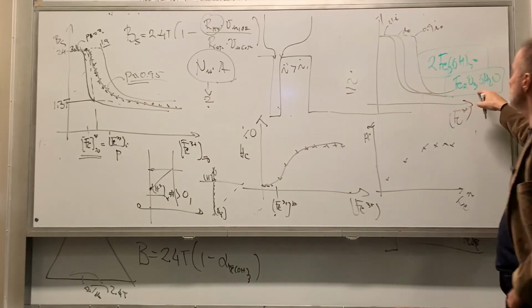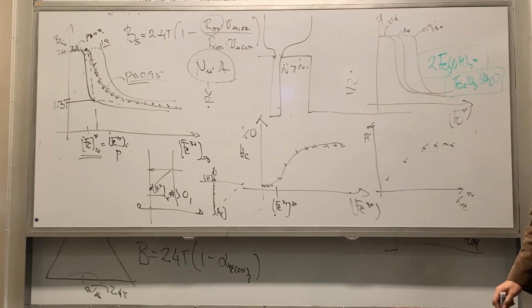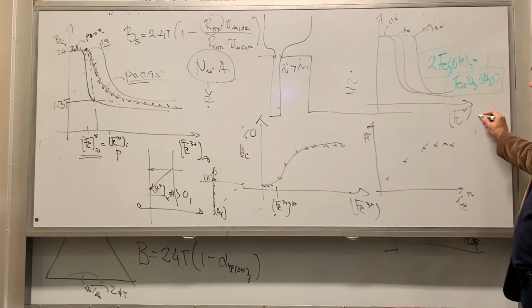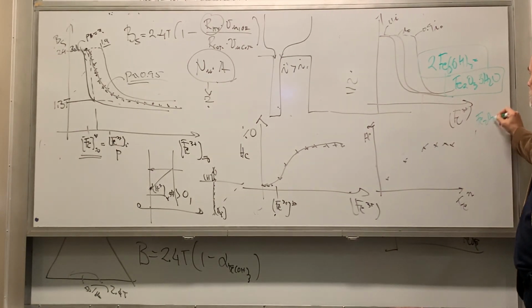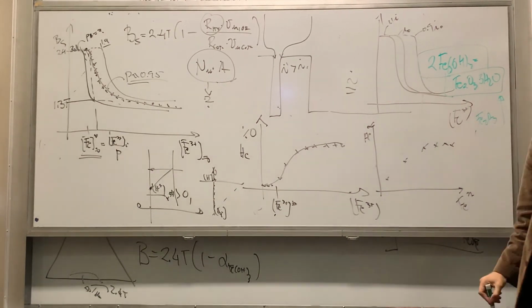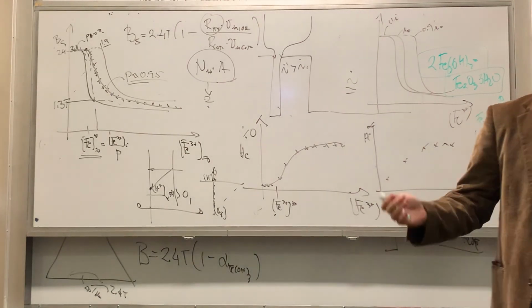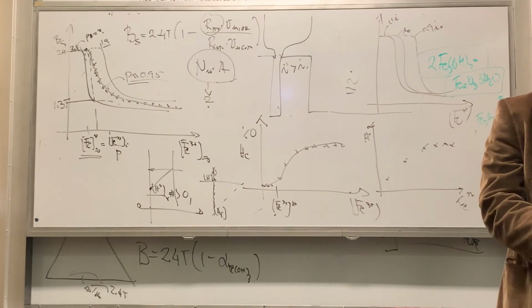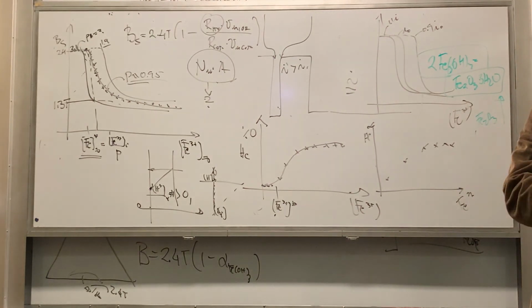It's a hydrated Fe2O3. So if you have a hydroxide and you just heat it up, you end up with Fe2O3 where the water is liberated. If you let it cool and the moisture in the air is significant, it will rehydrate again. There's basically an equilibrium between the hydrated forms, so that's what it is.